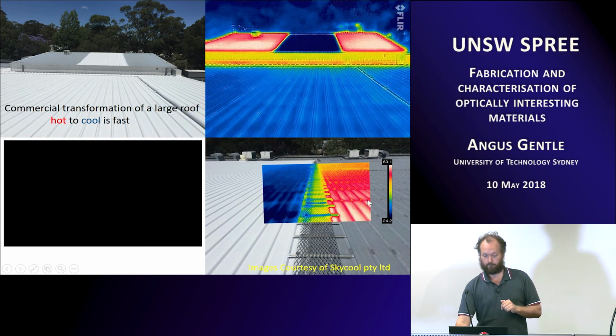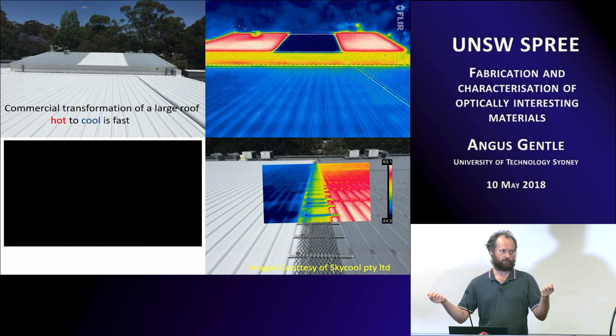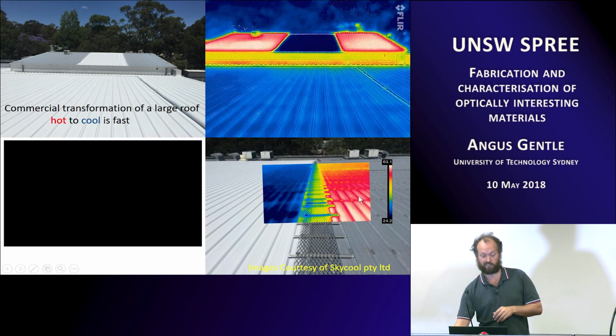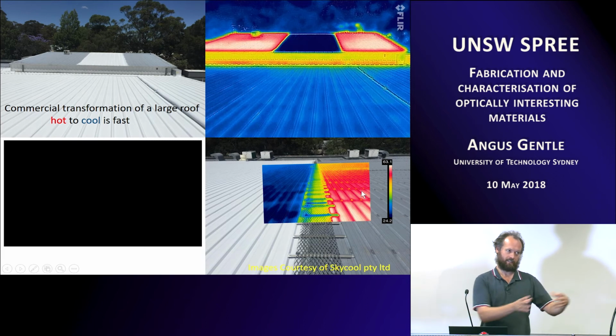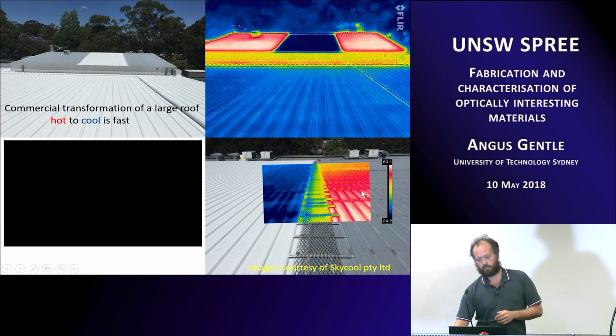That's pretty good. This is a standard old zinc aluminum roof where it's aged, so it absorbs a fair bit. The emittance is about 0.5, so the actual temperature is really hotter than that, because the cameras are set up for 0.95 emittance, which is about the same as the paints. So you can see a couple of interesting effects. One, cool roofs work really, really well.